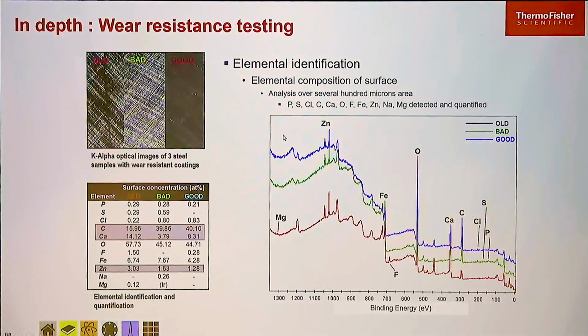Again, first step, let's get a survey scan and understand what elements are present. We can see here we've got phosphorus, sulfur, chlorine, carbon, calcium, oxygen, fluorine, iron, zinc, sodium, and magnesium. And we can see differences in the amounts of these in the 3 different samples. The zinc level is a bit higher in the old sample. If we look at the calcium level, it's highest in the old, about halfway in the good, and very low in the bad. So that could be an area to investigate. And the carbon levels are quite different as well. So these are elements that we'll maybe focus on to try and understand what's going on with the sample.